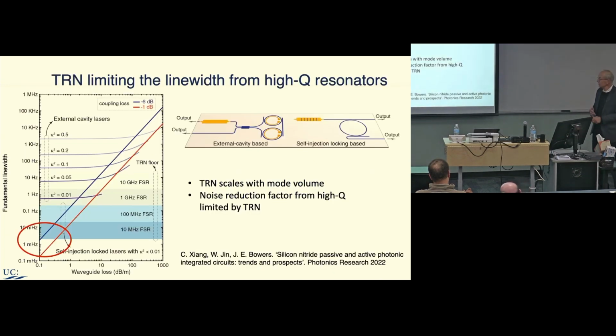So this shows sort of where we should be. We are today at 0.1 dB per meter, we routinely get that out of 2 different foundries. At that point, we should be at roughly 1 millihertz Lorentzian linewidth out of these lasers. Today we're about 40 millihertz, so we're up here somewhere. But everything fits this line pretty well, we just have some excess losses in the cavity that end up making it worse than it should be.